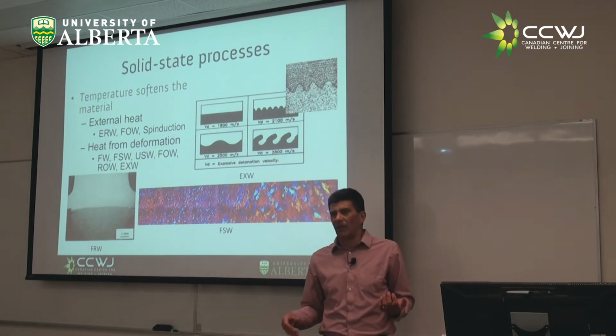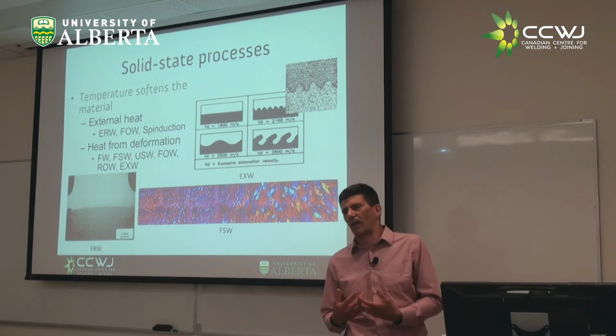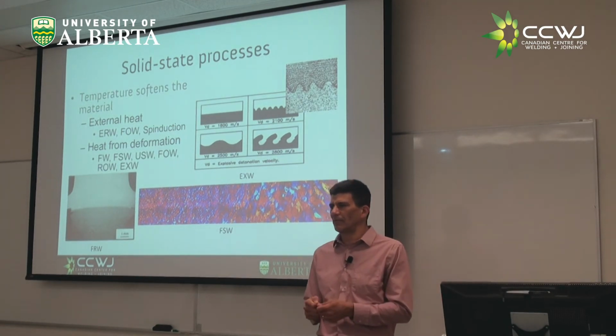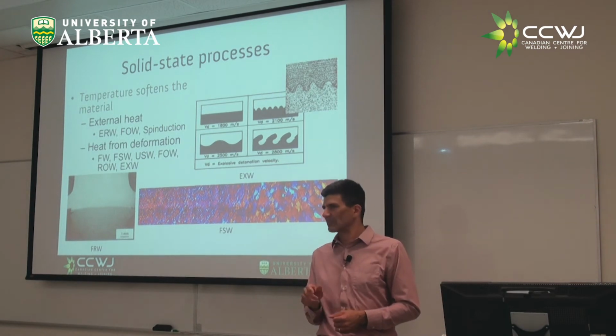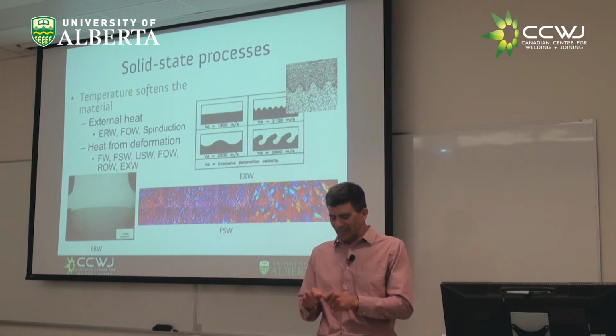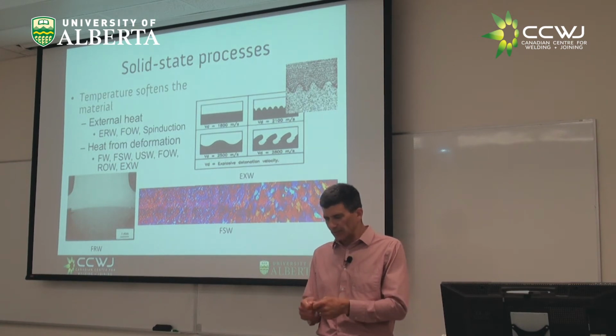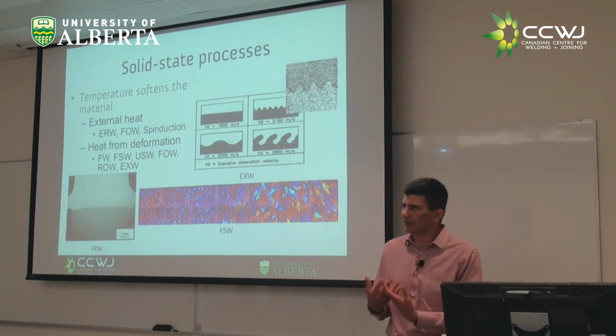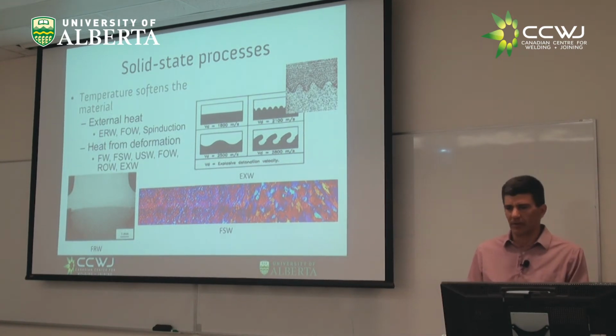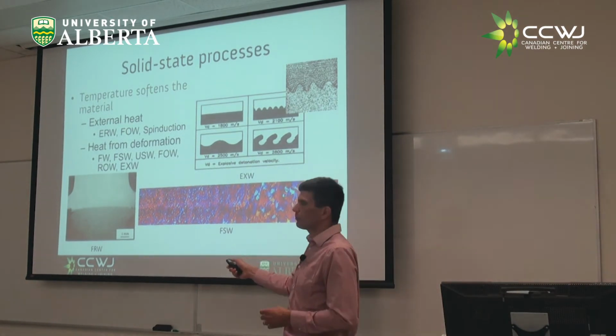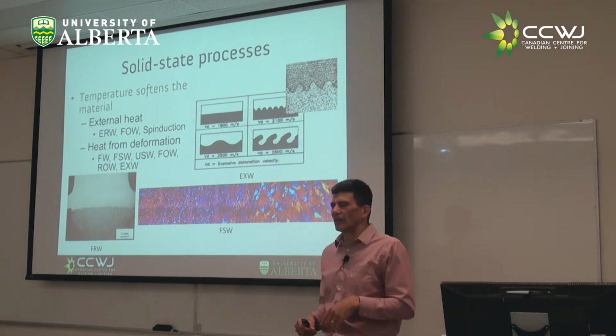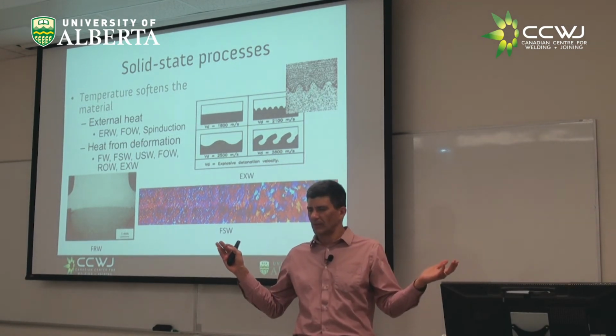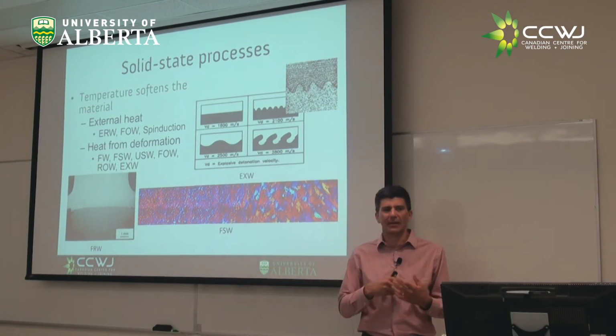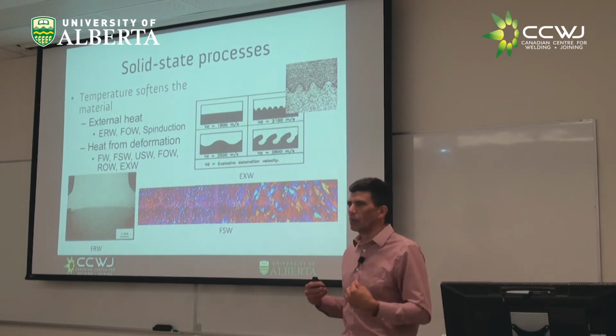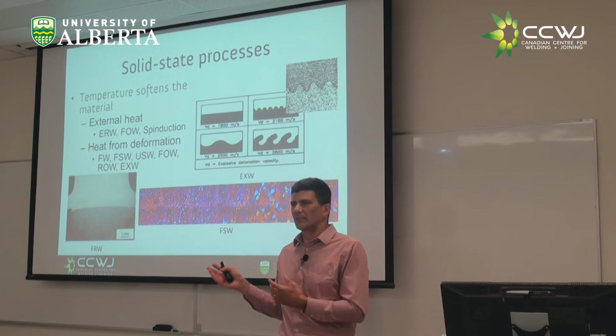Now, there are other processes in which the heat comes from the internal heating from the deformation, right? If you get a paper clip and you bend it enough times, it breaks. But if you have done the experiment, you also realize it gets really hot at the bending point, right? That heat, where does it come from? It comes from all this force and this displacement you make. This mechanical energy you put in is transformed into thermal energy. So there are processes like friction stir welding, which you're going to see in our lab in action, in which you don't put any external source of heat, but the thing gets hotter, right? And it's because you're mechanically deforming it. All these acronyms, and I'm aware, mean nothing to you right now, right? It might seem impossible to remember them.